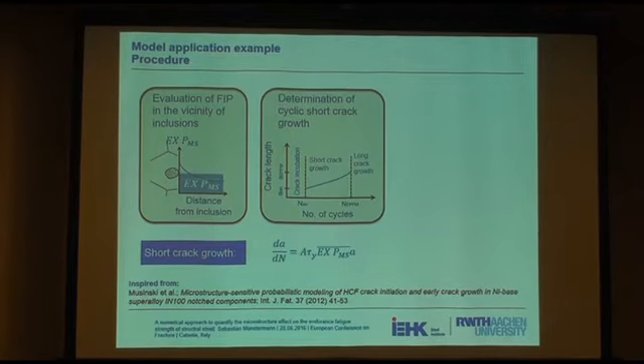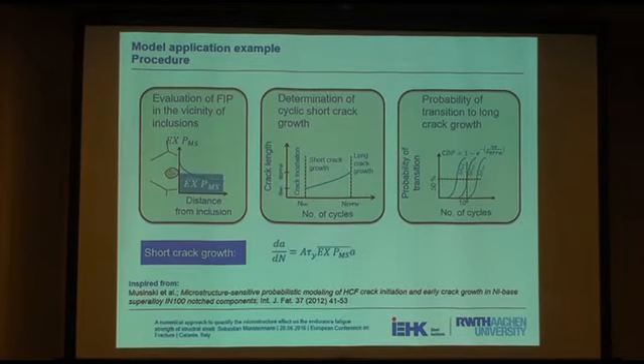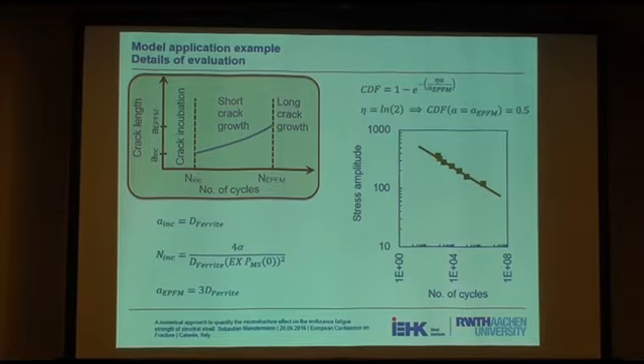Okay, so we can express the fatigue indicator parameter in the zone very close to the inclusion. There is also a certain crack propagation law available for these short cracks, a kind of da/dN rule, similar to the Paris law. And of course, with increasing length of this short crack, it becomes more probable that the crack will have a transition to a long crack. So also here we have to use a statistical description.